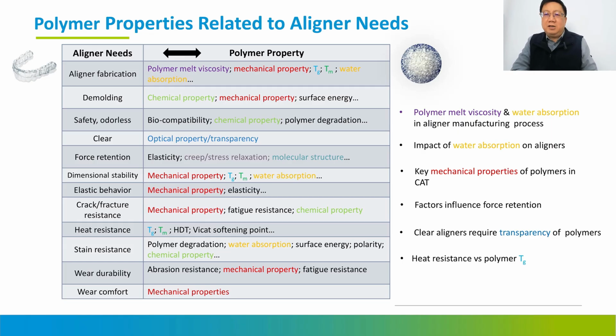Force retention needs a high Tg material. This is the reason some good materials use a much higher Tg, like the Tritan material. Based on this, the material is one of the key points for force retention. It maintains elasticity, and the quick reaction is much lower, and it also depends on how you organize the molecular structure. You can make more branched segments, which means the force does not go in just one direction, the force can dissipate to other areas, so that the elasticity can come back faster.